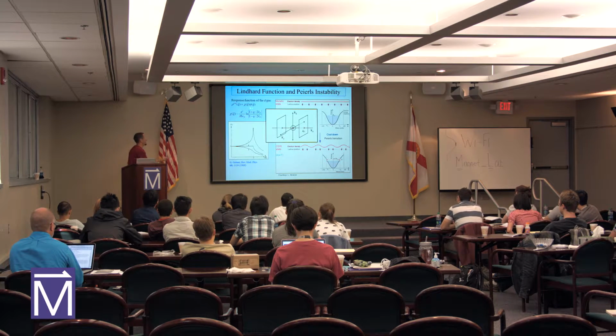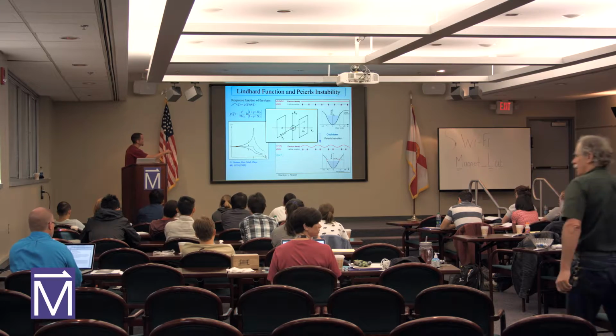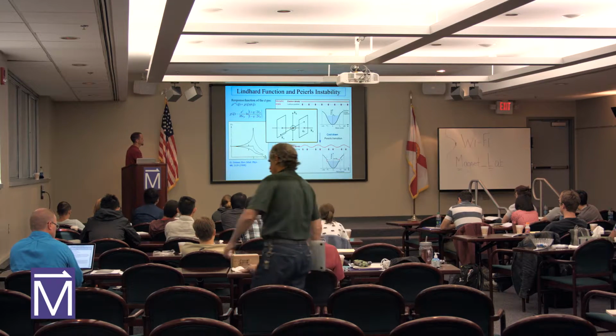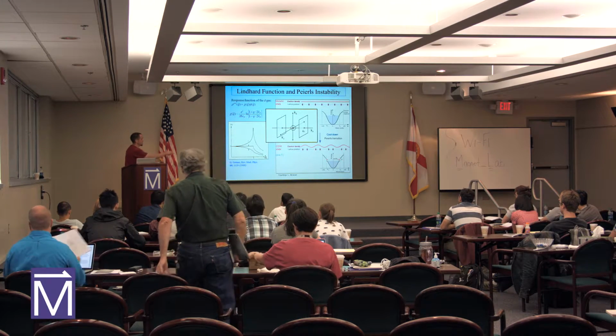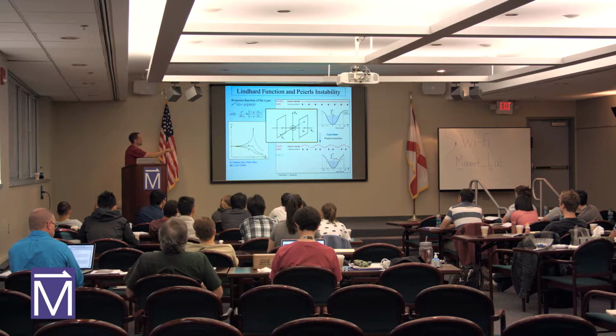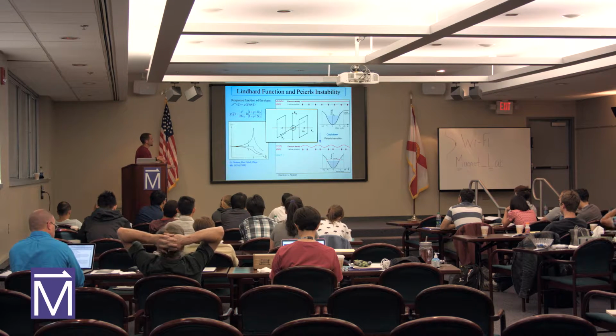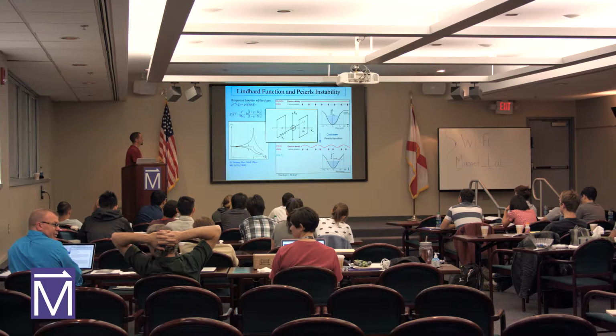These equations at the top basically talk about how an electron gas responds to the dimensionality of the material. What it really shows is that for the 1D case versus 2D or 3D, there's an instability when the Fermi surfaces are 2 kF apart. So in our one-dimensional Fermi surface case, because they're 2 kF apart, we have an instability against phase transitions. And very interesting things happen when we have this case.